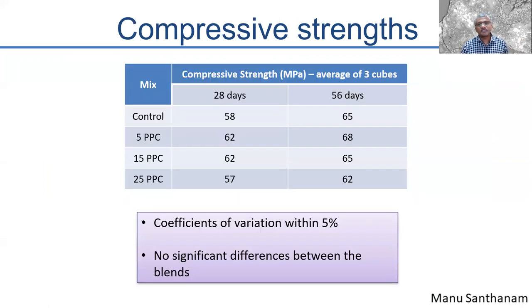You can see there's not much effect on strength as we change the bagasse ash content. So at 5, 15, 25% bagasse ash, the strength is within 5 to 10% of your control strength. Higher or lower does not really matter. Mostly they are within the same range as your conventional concrete, or control concrete with just OPC. So that means that your bagasse ash is performing at a level which is equivalent to the cement.